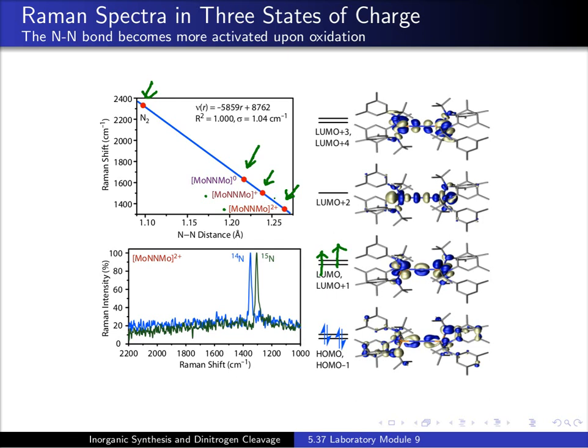And furthermore, that lengthening of the NN bond corresponds with a decrease in the energy of the NN stretching frequency as measured by Raman spectroscopy. And there's an essentially perfect correlation of the energy of the stretching frequency with the NN bond distance in these three complexes, the neutral, the 1+, and the 2+, and also extending to the N2 molecule itself. And so the NN stretching frequency is close to 2300 reciprocal centimeters in free N2, and then binding it to molybdenum decreases it to about 1640 reciprocal centimeters, and then oxidizing and lengthening the bond decreases the stretching frequency ultimately in the dication down here to less than 1400 reciprocal centimeters.